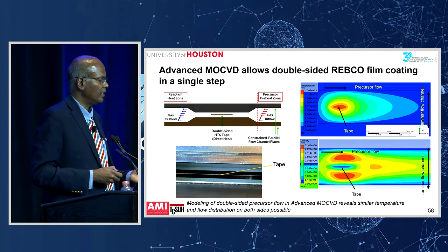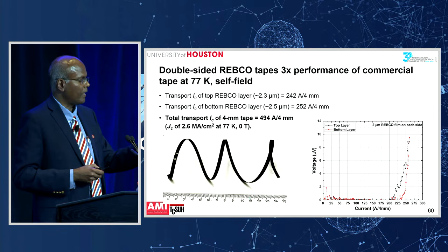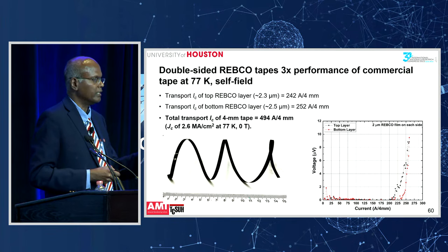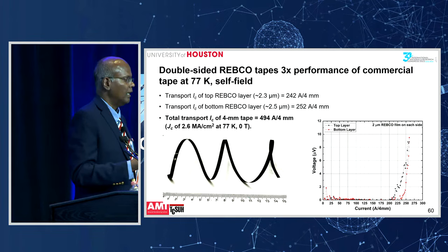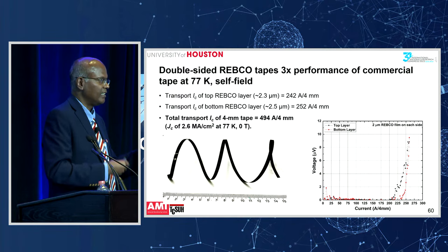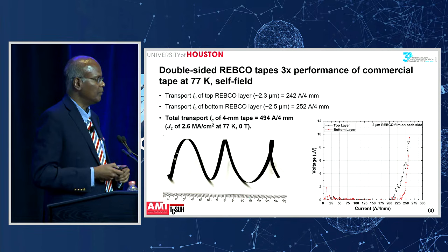So you can see there that on both sides, the black curve and the red curve on the two layers, top and bottom side, so now we can get double the performance by coating both sides of the film. So it's an epitaxial film, nanoscale engineered using the self-assembly process on both sides of the film. So that is what has been done recently with the double-sided tapes with advanced MOCVD.